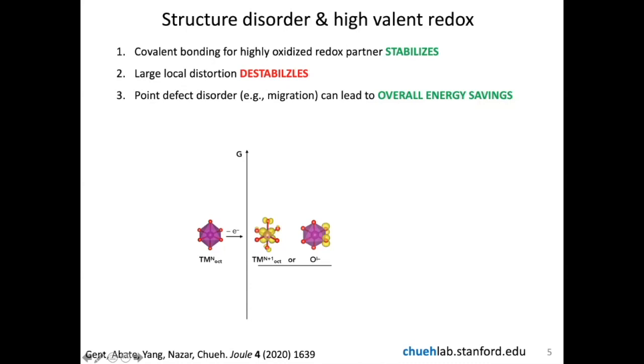When this occurs, the local distortion increases. You form very large local strain energy because you have both long and short bonds. And this can destabilize the material, adding to the overall energy. But what really comes to save the day is that if you allow some disorder in the system, for example, the transition metal migration, you can actually allow the strain energy to be accommodated. And this is what I'm showing here.